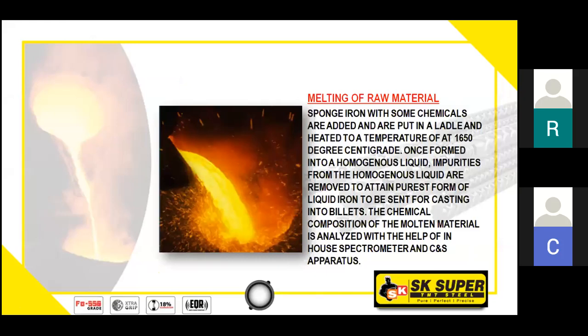First is the melting of raw materials. Now, sponge will come to the plant from various sources. Some big people like JSW, SAIL, Tata have their own sponge plants and iron ore mines. But basically, the sponge which is present at the plant is lifted up with the help of a magnet. Before putting it into the melting process, a 5 kg sample of the sponge iron is taken. It is melted in a small 5 kg furnace, as we call it in technical terms. It is heated to a temperature of 1650 degrees, where the sponge iron melts and becomes like lava.